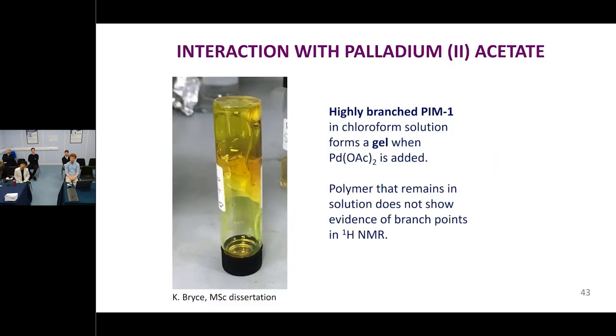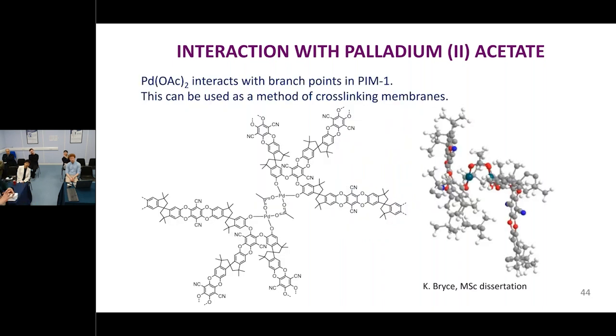Branched PIM1 behaves in some ways differently to less branched PIM1. For example, if we add palladium acetate, it forms a gel. A more linear PIM1 won't. In fact, if we analyze the bit of the polymer that hasn't gelled, we see it hasn't got the branch points. So what's happening is we're getting coordination at those branch points. Palladium acetate is interesting because it can form triangles, it can form polymers. And so it looks like we're getting cross links, something like this. And we can use that.